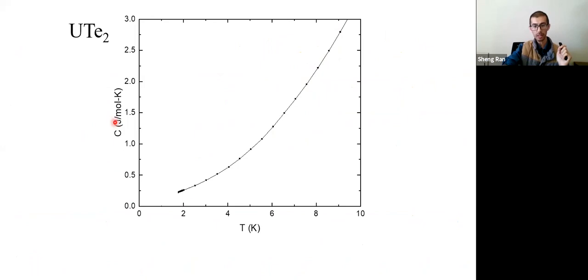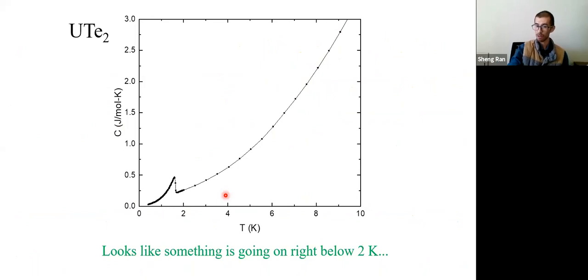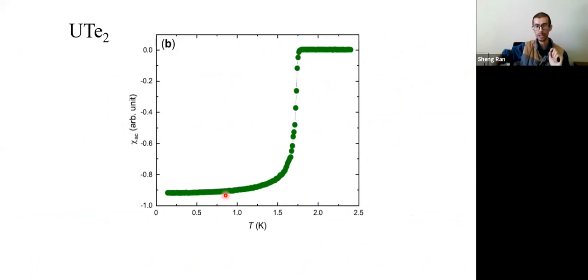Here I'm showing specific heat as a function of temperature above 1.8 K. This is very consistent with the literature report. Now we can cool down a little bit more. And when you do this, there's an anomaly indicating there is indeed a phase transition below 2 K. What is this phase transition? So we did AC magnetization. In AC magnetization, this really looks like a textbook Meissner effect. It looks like a superconductor.